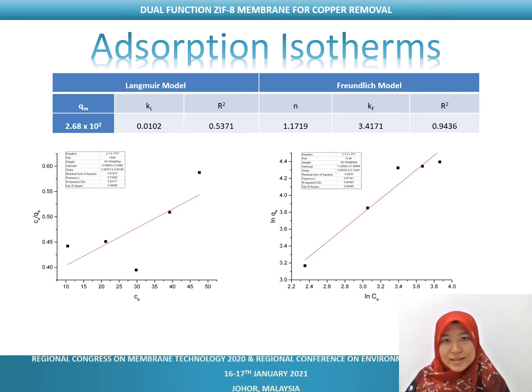On the other hand, n describes the interaction occurring during the adsorption process. If n is more than 1, it indicates chemical interaction, whereas when n is below 1 it shows physical interaction occurred. In this study, the value of n is equal to 1.1719. Therefore, the interaction between copper-2 and the ZIF-8 membrane could be denoted as a chemisorption process.